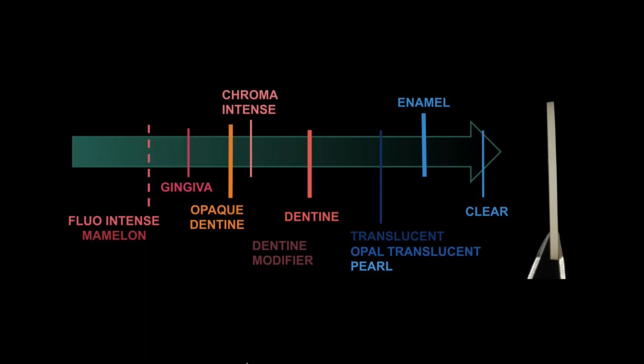And I wanted you to notice that I said when you add fluorescence to the material, how it really changes the opacity of it. And it changes it because of the optics that happen when light hits the fluorescent materials and becomes more reflective. So what's nice about that is it seems like it's a more opacified material. I would argue that it's not necessarily more opacified, but it is definitely appearing more opacified in a light perspective